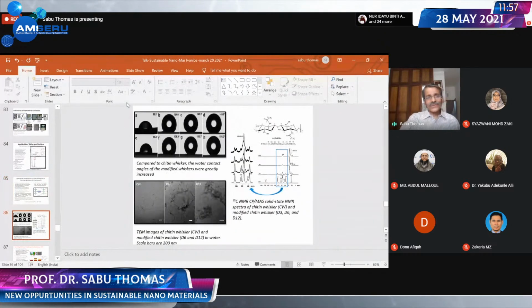You look at this. This is a neat nanochitin. Look at the contact angle, 86.5. As you increase the number of alkyl groups, you see a progressive increase of contact angle. The highest value goes to 158.2. So you can make hydrophobic chitin, just by having a lot of alkyl groups.